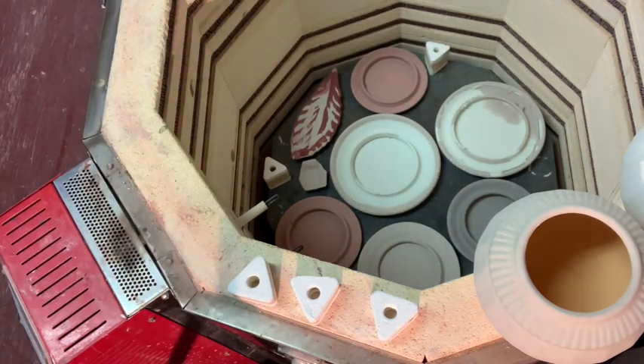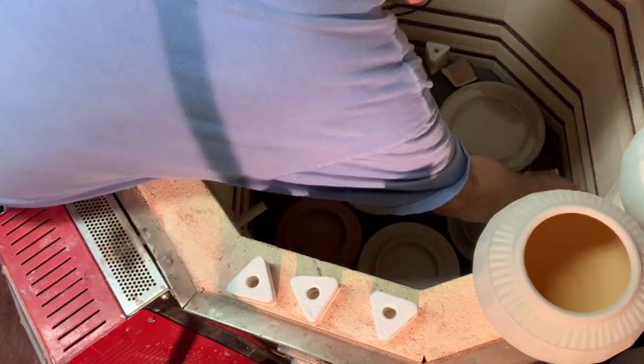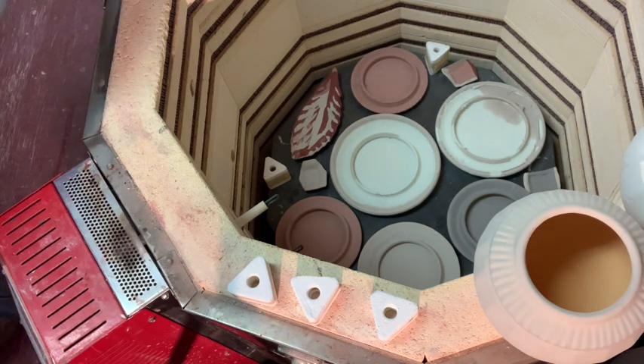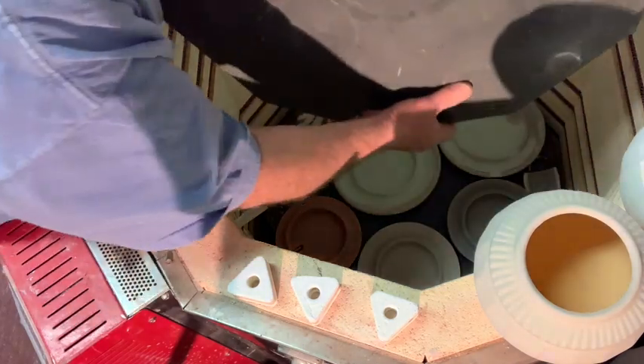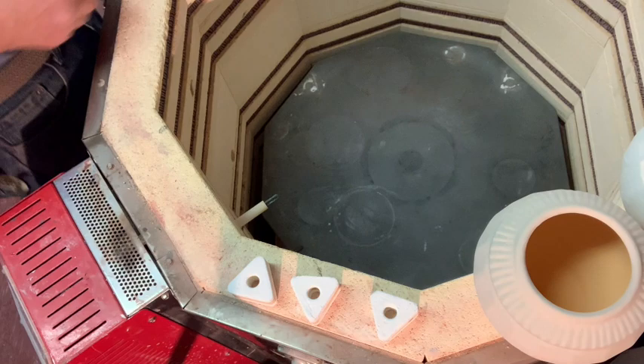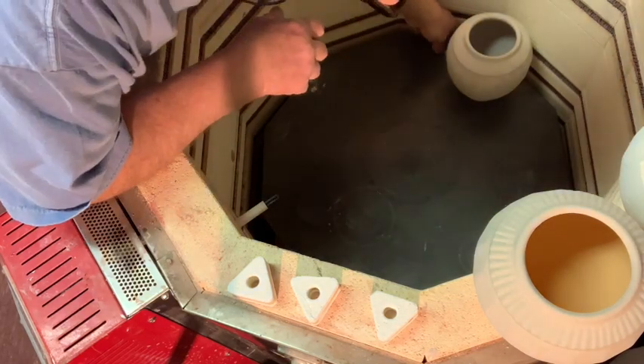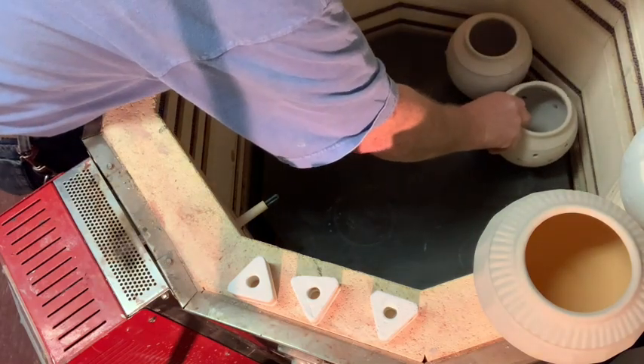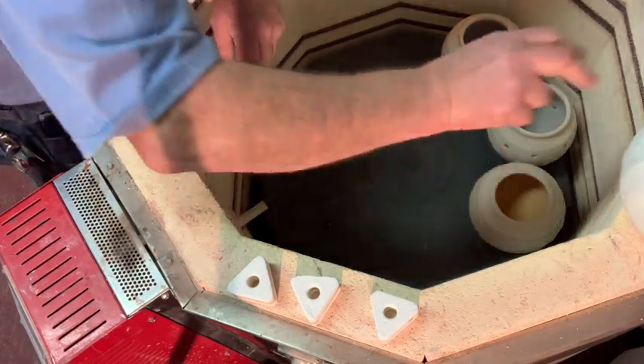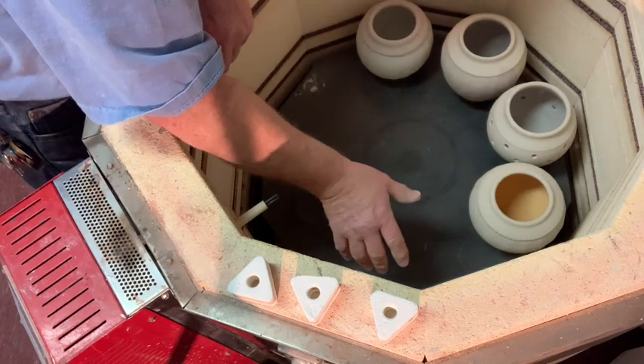There's space over there for a couple too. I have friends who have children who make little rabbits and hedgehogs out of clay, and they use those to fill in these spaces. I pre-wiped all my shelves and sanded them so there's no loose stuff, so we can just get these right down in there. There's a gap with no elements, so I'm going to go back to packing jars in there, leaving an inch from the edge. If you get it too close to the edge, you might burn or boil the glaze if it gets too hot. I can put them straight down without checking because I've wiped everything ahead of time - you should always check if you're not sure.